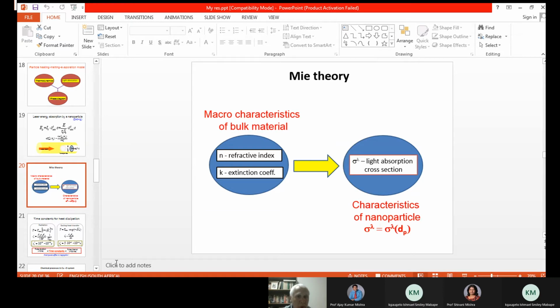Only when the particle became very small, a nanoparticle, the result of the Mie calculation became very important. And this paper published by Mie shows that using the macro characteristics of the material, n and k, the absorption coefficient and refraction index, these two electromagnetic characteristics of the bulk material, it's possible to exactly calculate the absorption cross section for different sizes of nanoparticles.